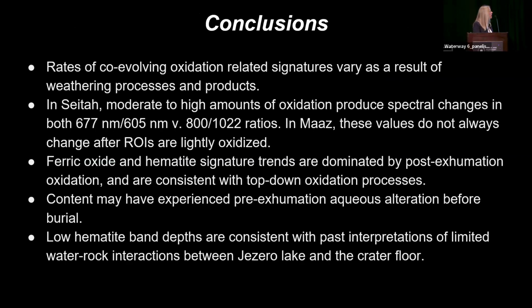So in conclusion, the rates of those co-evolving spectral signatures do vary as a result of the weathering products produced. And in Seta, moderate to high amounts of oxidation do produce changes in both 677/605 and 800/1022 ratios, but those are not very distinguishable after initial stages of oxidation for Moz and Contant. And ferric oxide and hematite signatures also trend such that they appear to be dominated by post-exhumation oxidation and are also consistent with top-down oxidation processes.